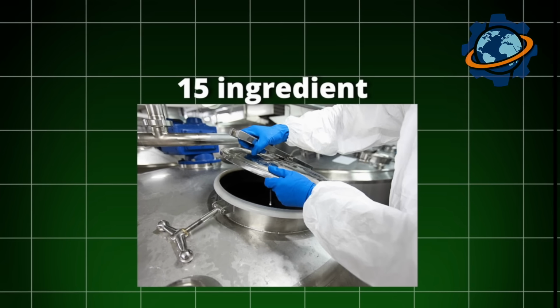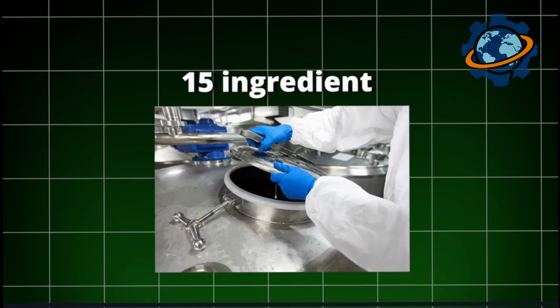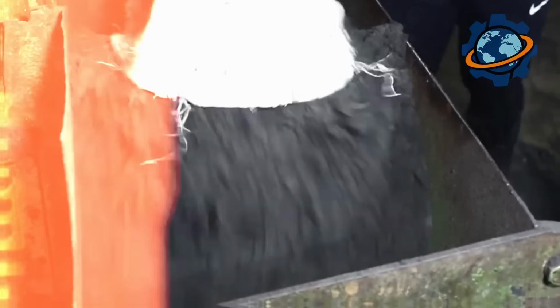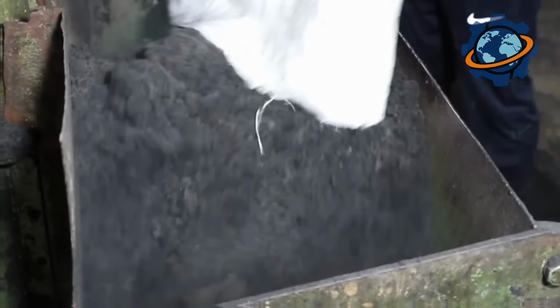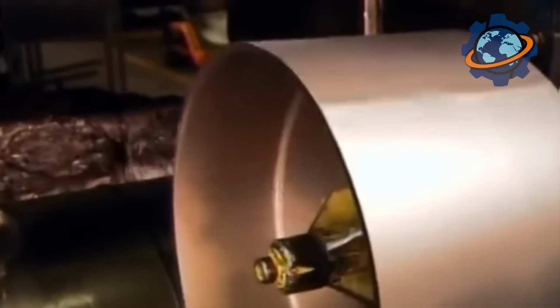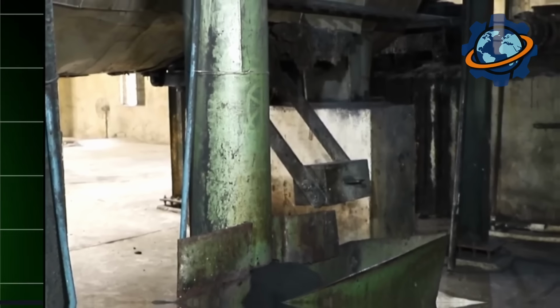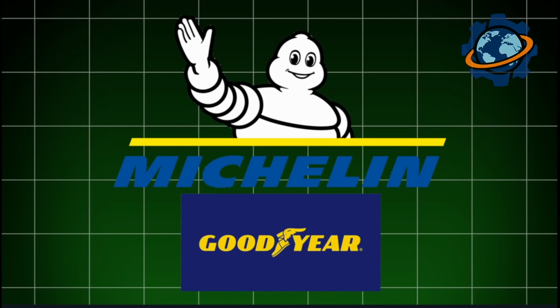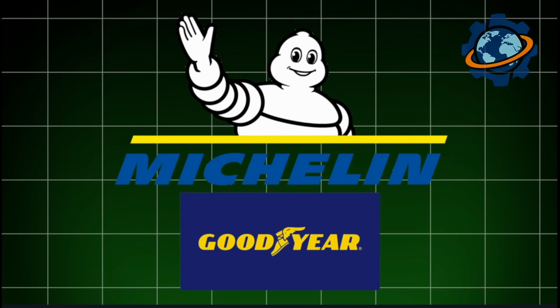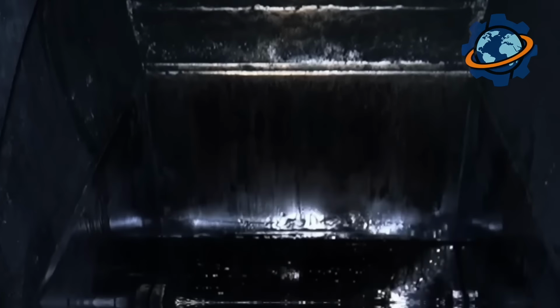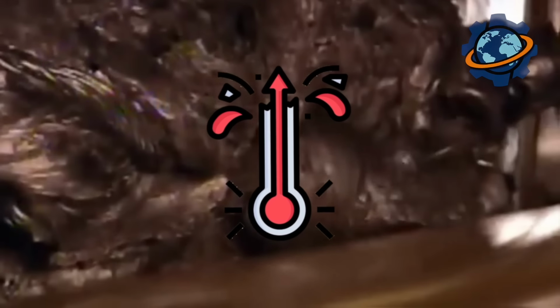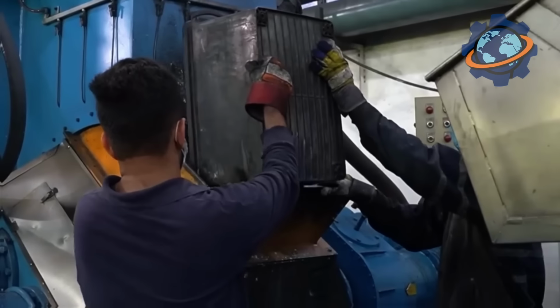Each tire compound contains 15 ingredients mixed in precise ratios. Tread rubber emphasizes durability. Sidewall rubber prioritizes flexibility. Inner liner uses butyl rubber for air retention. Formulations remain trade secrets. Michelin's compounds differ from Goodyear's, creating performance variations. Mixing takes 12 minutes at temperatures reaching 300 degrees Fahrenheit. The batch, weighing 500 pounds, emerges as uniform black mass ready for shaping.